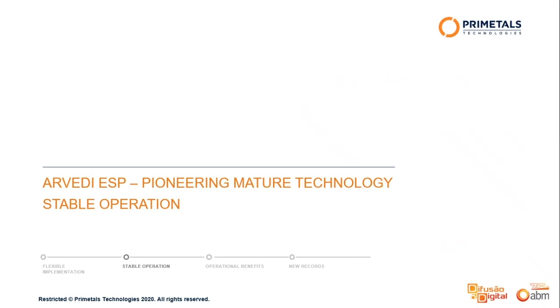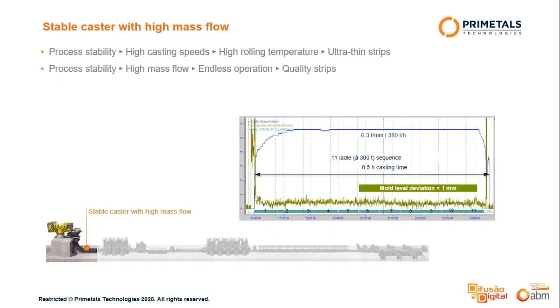Coming now to the operation. The biggest plus of the Arvedi ESP line is its stable operation. It starts already at the caster, even at highest mass flow of 380 tons per hour, as you can see here. Performed for 8-hour sequences with more than 3,000 tons, the mold level deviation is below 1 millimeter. This gives perfect stability, and this high mass flow is the basis for high rolling temperatures, endless operation, and thus quality strips.